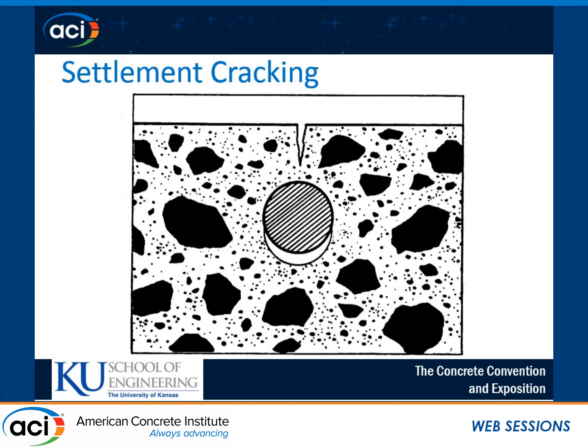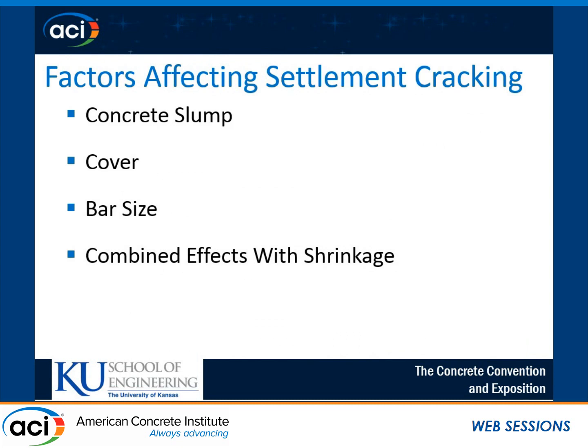So here's a cross-section of a piece of reinforced concrete with a piece of reinforcing steel in the middle. This steel acts as a restraint in our cross-section here. So after fresh concrete is placed within our forms, it's going to flow over that piece of rebar. And the mechanism of settlement cracking is that you have the solid particles in this mixture settling down to the bottom, and then you have bleed water rising to the top. And as that concrete hardens, you have local tensile stresses that develop in the top and make you more prone to have cracking directly over those bars. Not a good thing.